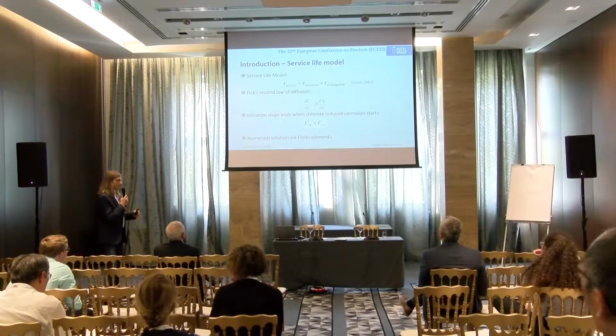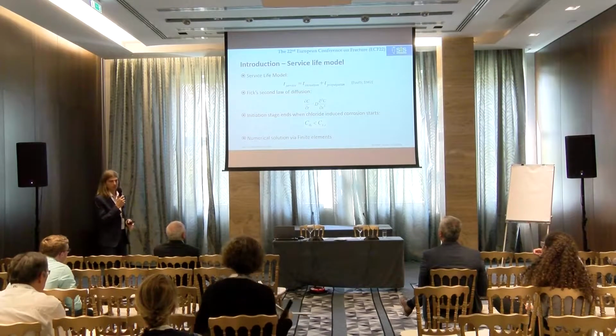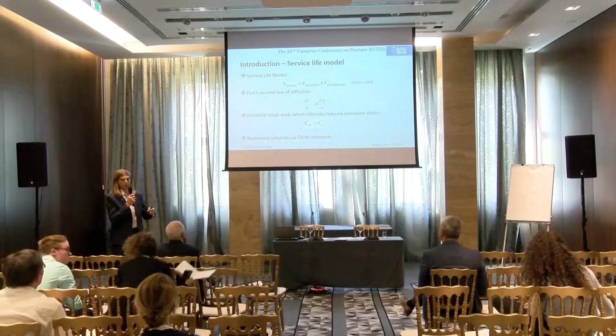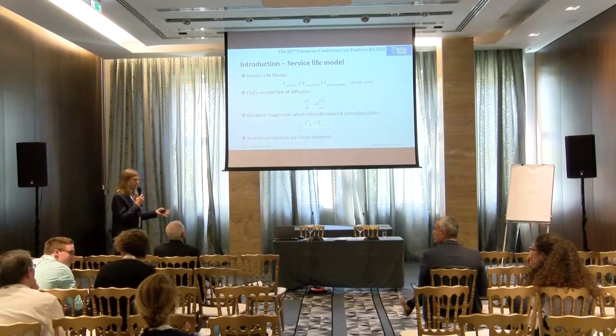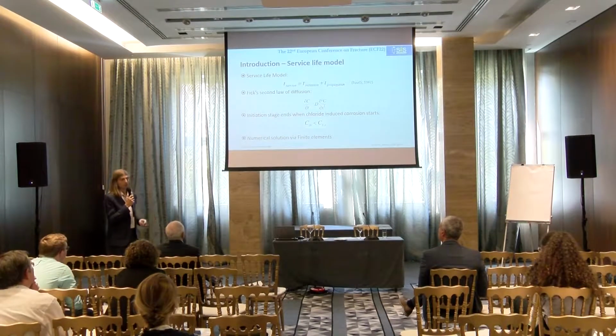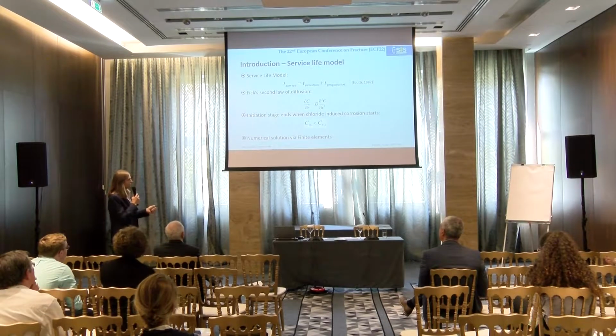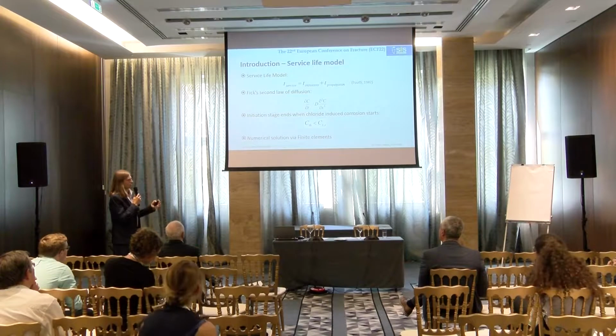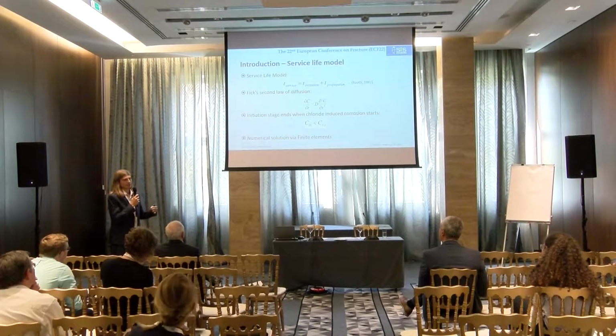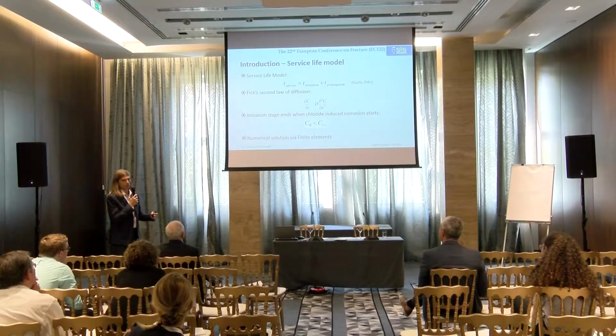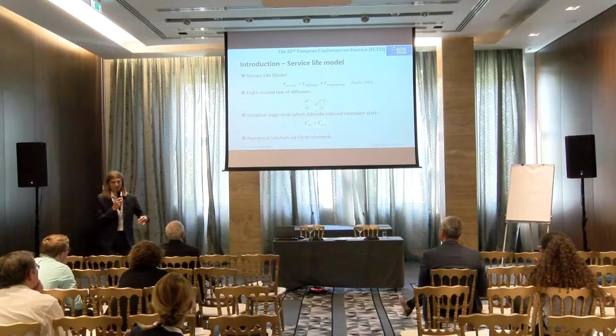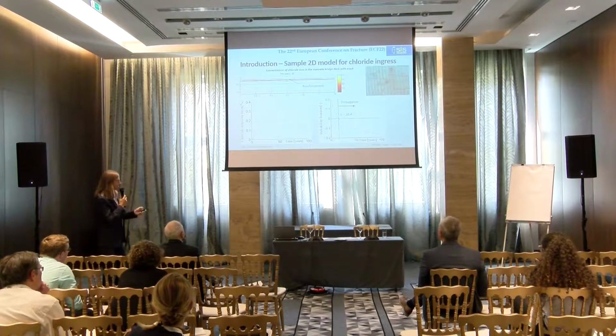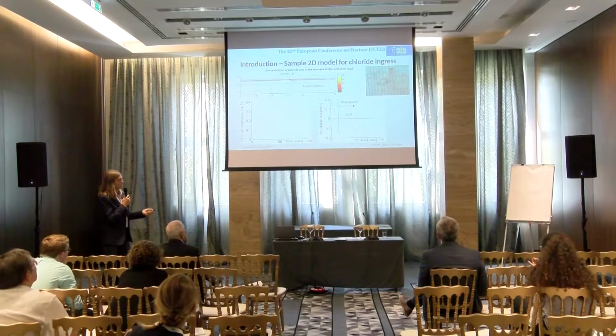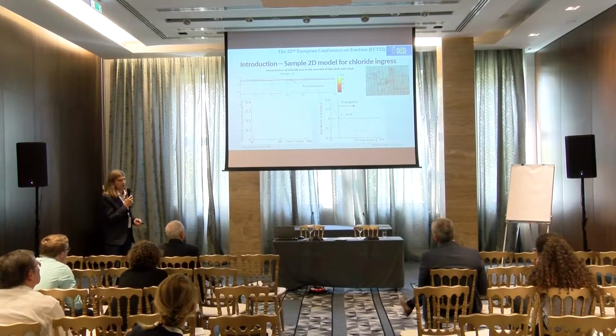So if we have the concrete, which is the structural material, it can be, for example, on the highway bridges, and this is exposed to, for example, winter de-icing or the marine environment. The structure is exposed to chlorides, they penetrate, and we can, in a simplified way, model the chloride penetration by the second Fick's law of diffusion. And when the concentration of the chlorides at the level of the reinforcement is too high, then the corrosion starts to propagate, and the initiation period is exploited. So this is a sample of the 2D model built in MATLAB that we use.